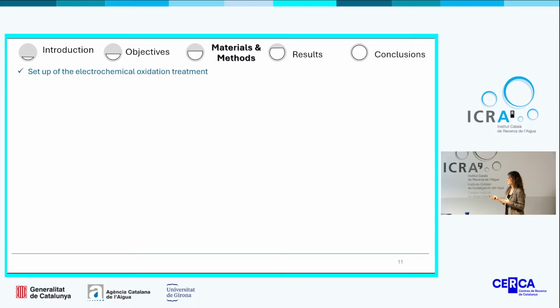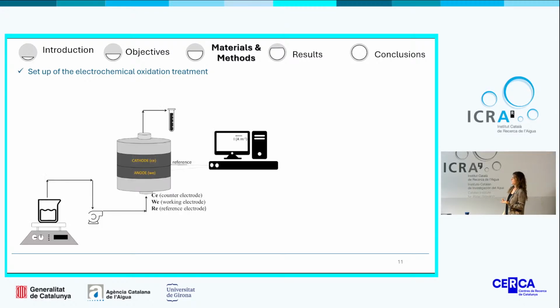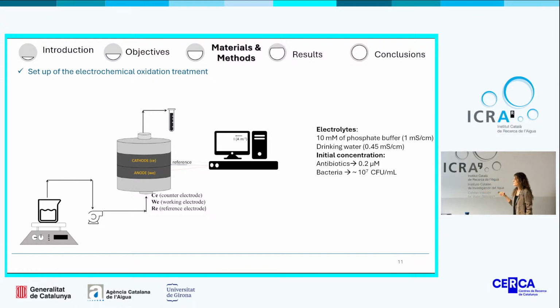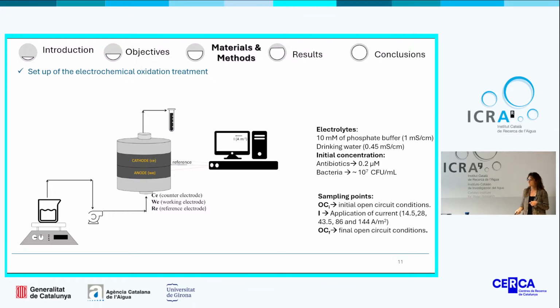different chapters. The setup of the electrochemical oxidation treatment is presented here, and the mother solution was prepared using 2 different electrolytes, 10 millimolar phosphate buffer and drinking water. The initial concentration of antibiotics was 0.2 micromolar, and in case of bacteria, approximately 10^7 colony-forming units per milliliter. We were sampling at 3 different points: during the initial open circuit conditions, in order to study the absorption of antibiotics or also the elimination, inactivation of bacteria, then during the application of current, and during the final open circuit condition to evaluate as well if we were electrosorbing our contaminants.